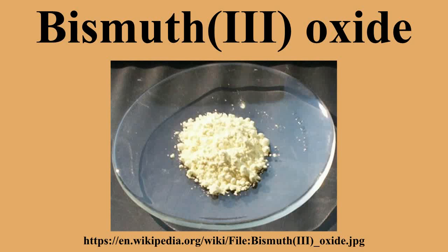The arrangement of oxygen atoms within the unit cell of bismuth trioxide has been the subject of much debate in the past. 3 different models have been proposed. Sillén used powder X-ray diffraction on quenched samples and reported the structure of bismuth trioxide was a simple cubic phase with oxygen vacancies ordered along the <111> direction, along the cube body diagonal.